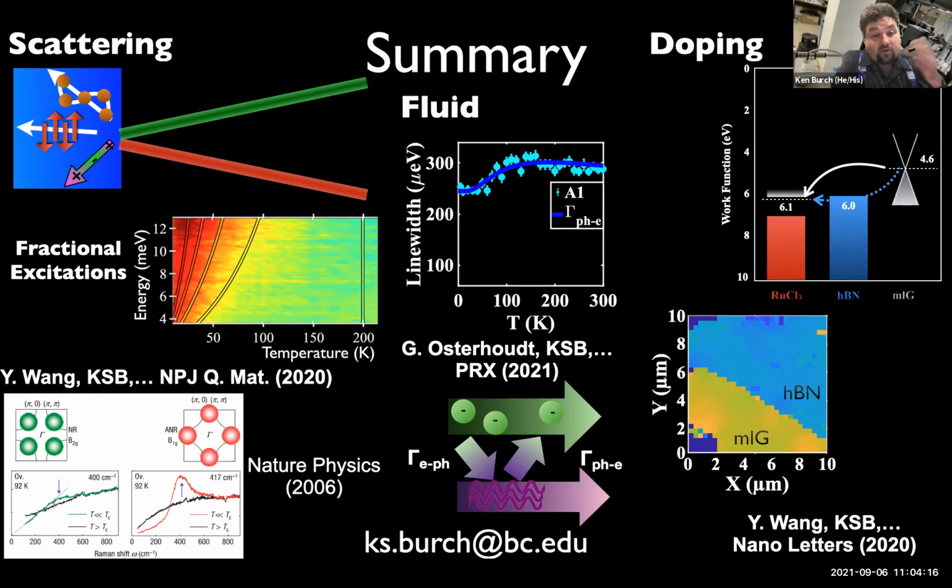They're not enormous, they're like 5,000, because at this heavy doping level, you have a lot of electron-electron scattering, at least at low temperature. And then of course it gets worse with electron-phonon scattering. So I don't think we're seeing anything remarkably different than what's been seen in transport in graphene in that sense.